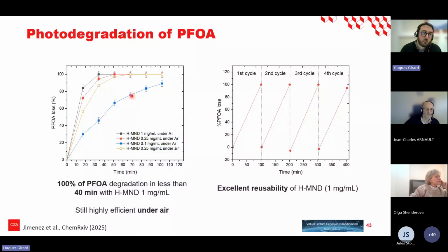We also, of course, studied the effect of the concentration. So, of course, if we increase more and more the concentration of the milled nanodiamond, you will increase the efficiency. And finally, at 1 milligram per milliliter, which is not that much, we obtained 100% degradation of the PFOA in less than 40 minutes. And if you look in the literature, if you compare with comparable conditions like the concentration of PFOA, the solar type illumination, and so on, this is a very excellent result. So these nanodiamonds are really promising for that.